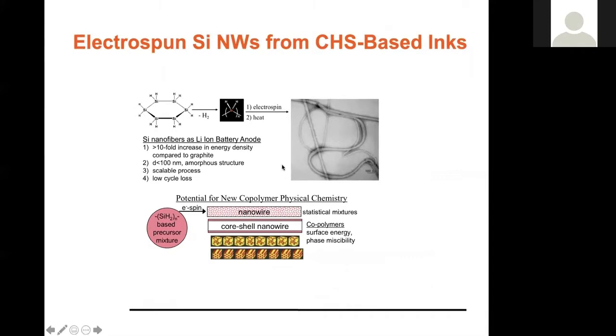Just going back to the silicon nanowire example, they can be made with diameters less than 100 nanometers. And this 100 nanometers, or actually below 150 nanometers, is critical to one thing that's been a challenge in the past with silicon-based materials in anodes: the volumetric expansion leads to rapid loss of cell stability. But because CHS leads to materials that have well-defined size and morphology, we can avoid a lot of these issues by making these nanoscale materials. And these silicon nanofibers can be made in a highly scalable process.